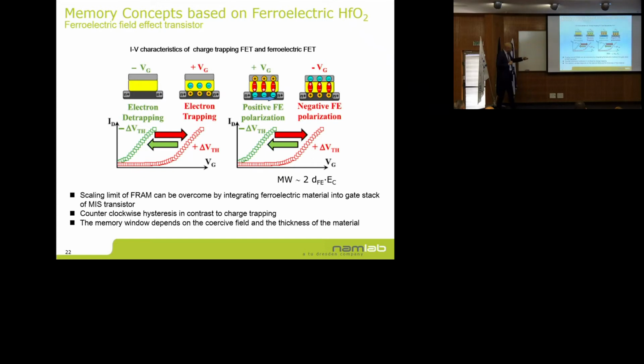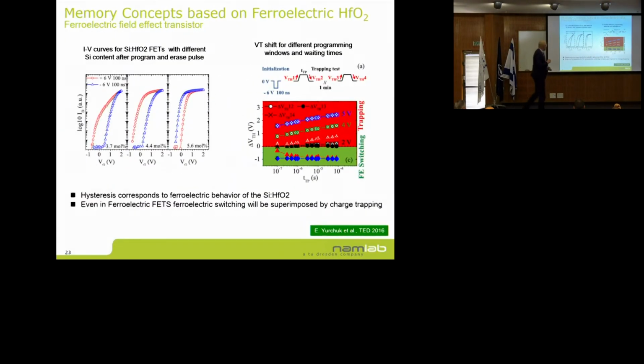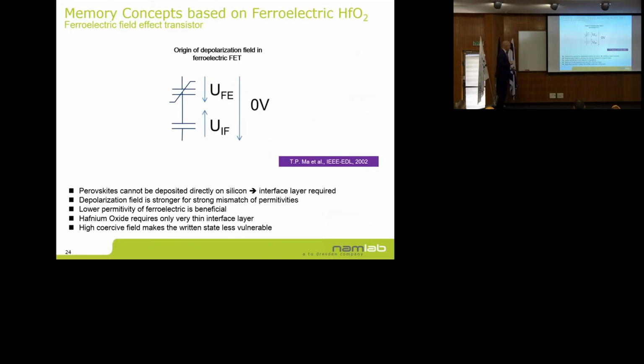And what's important here is the memory window is not defined by the polarization. If anybody is interested, I can explain afterwards, because some people seem to be surprised by that. The memory window is defined by the coercive field multiplied by the thickness of the film. And I skipped this one because of lack of time.